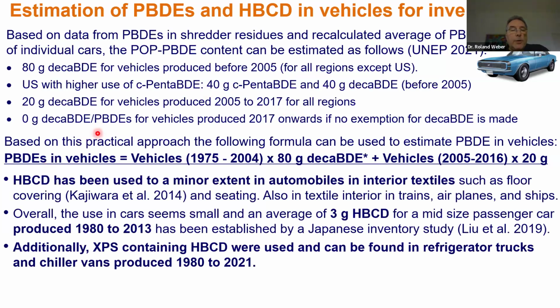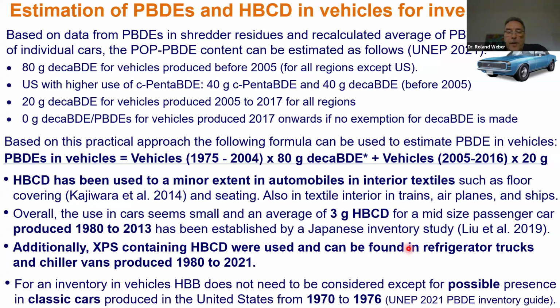And also in Japan, they have developed for HBCD an impact factor. So this was minor use, and in total, the average concentration was around 3 gram of HBCD in vehicles. This means only about 5% of the PBDE amount. So you see also for the transport sector, HBCD, which was a big flame retardant, is not so relevant for the transport sector.